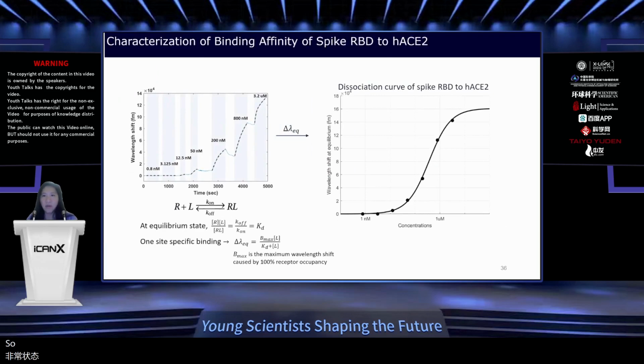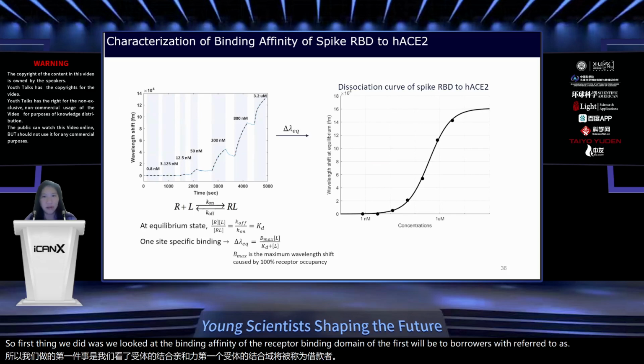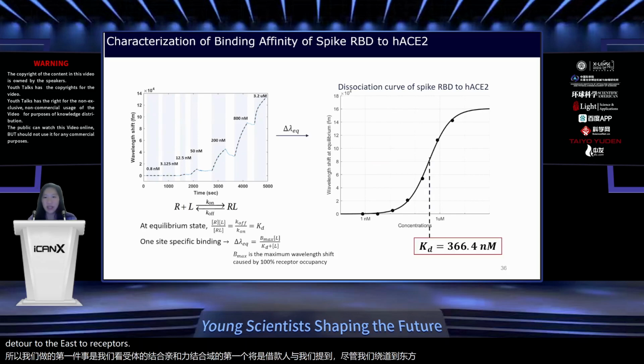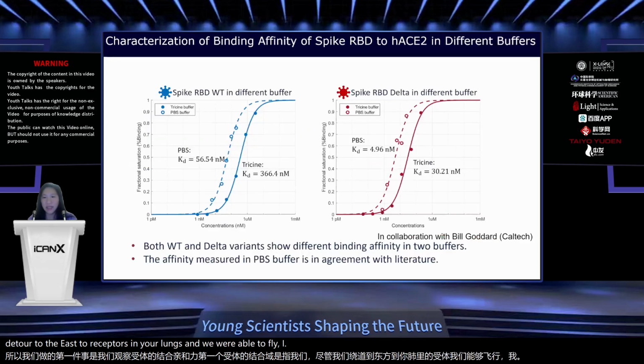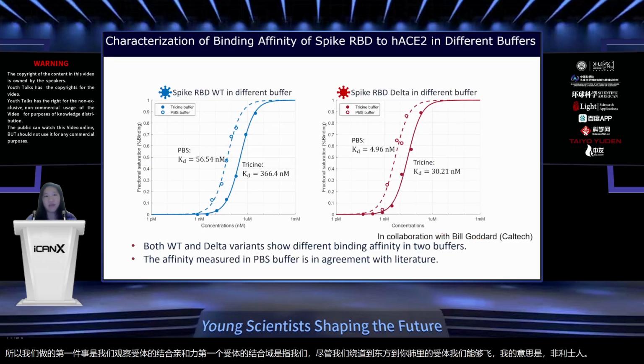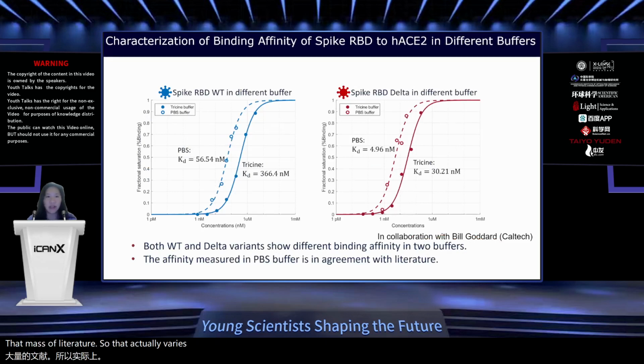So the first thing we did was we looked at the binding affinity of the receptor binding domain of the SARS-CoV-2 virus, which we refer to as the spike RBD, to the ACE2 receptors in your lungs, and we were able to pull out binding affinities that match with literature. So it actually varies depending on what buffer you use. So this is Tris-tricine buffer, and we also did PBS. And what we did in PBS matched with literature. There aren't other people who did this in Tris-tricine buffer.